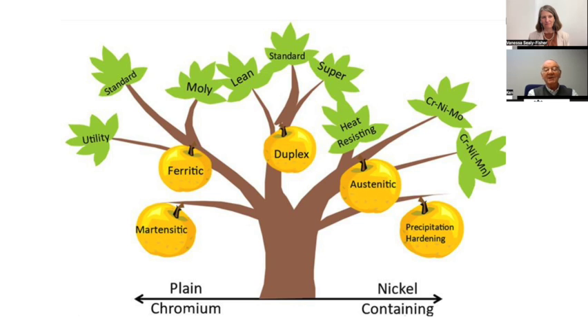And then as we move to the right-hand side, we've got the so-called super duplexes, which have even more chromium, nickel, and molybdenum, nitrogen, etc. As you increase what we refer to as the austenite formers, which are your nickel and nitrogen, so you can increase your ferrite formers, which are your chrome, molybdenum combination. So I think that's in summary. And as you're increasing those alloying elements, so you'll increase corrosion resistance, most particularly your pitting corrosion, your crevice corrosion, and your stress corrosion cracking resistance. Right. So they really do start to become super duper, if I can use that term.